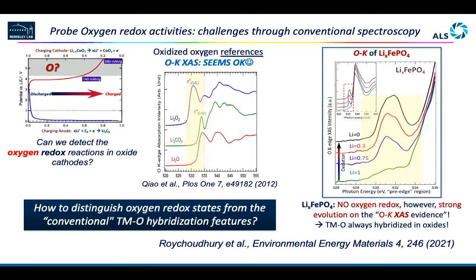So the reason is this lithium iron phosphate, I showed you that beautiful butterfly, so that is a purely iron redox material. There's really no oxygen redox involved here. But if we look at the pre-edge of this oxygen K spectra, you see from the discharge to the charge, this is so far the strongest change you can find in any battery materials. However, it's also a material that has no oxygen redox.